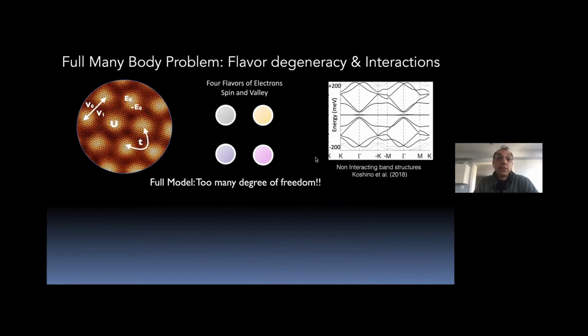But now you have to take into account that we have the flavors of the electrons, the spin and valley degrees of freedom. So you can think about this in real space as the Moiré sites being a bunch of quantum dots. And these quantum dots have hopping between them. That's the width of the flat band. The energy of the flat bands, you can think of them as E naught and minus E naught. And then you have on-site and nearest neighbor Coulomb repulsion in the system. This is a very, very difficult problem to solve. The full many-body problem here is even harder than the cuprates.